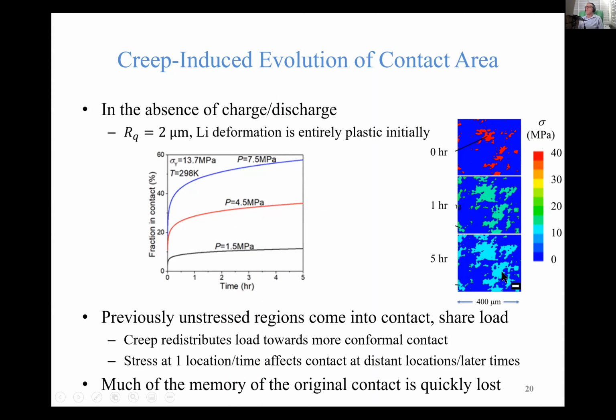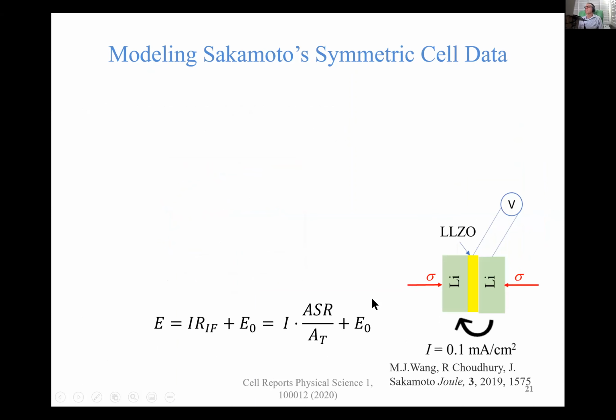Here it is after 5 hours, and what you can see is that the stress at one location can affect the stress at distant locations and at much later times, which is why you need long times and large regions if you're going to understand the mechanics of lithium.